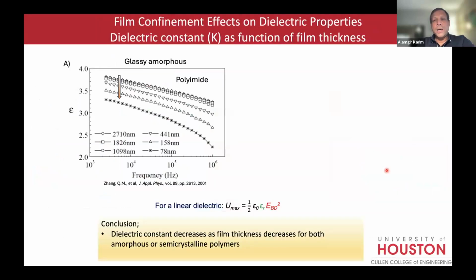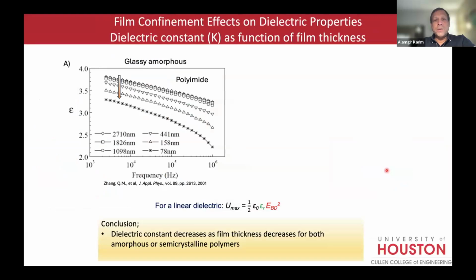All right. So let me first start with the dielectric constant. There are two parts: breakdown voltage and dielectric constant. It's linear in dielectric and typically square in breakdown voltage. So let's look at dielectric constant first. Then this is our literature. Okay, so you can see polyimide as you reduce, and we are talking now in a regime which is really thin. So sub-micron thickness is the region of interest.